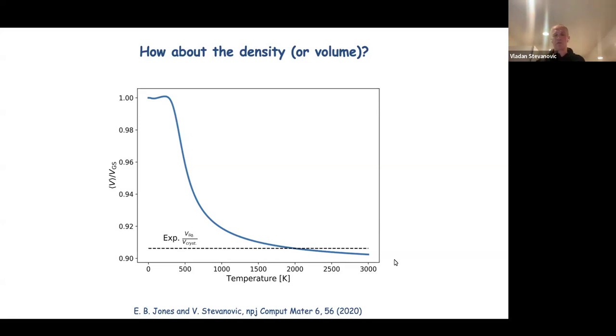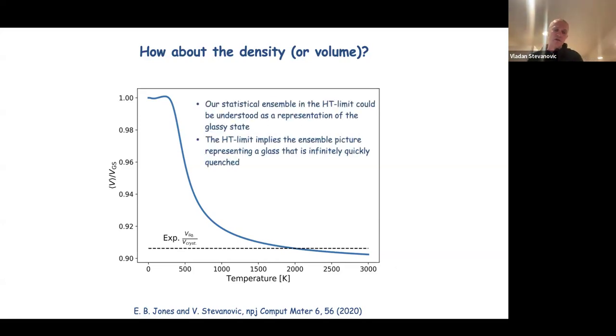to our average volume. So this prompted us to think a little bit further about what this all means and whether we could represent glasses, basically frozen liquids, using this methodology. And it seems from these results on silicon that our statistical ensemble in the high temperature limit could be understood as a representation of the glassy state. Why a glassy state? In my view, again, now we are entering the territory of philosophy, what we have is a fully ergodic system, so ergodicity completely assumed over all these local minima, but without kinetic energy. So in that sense, our ensemble picture, or the collection of these local minima, could be understood as an infinitely quickly quenched liquid.